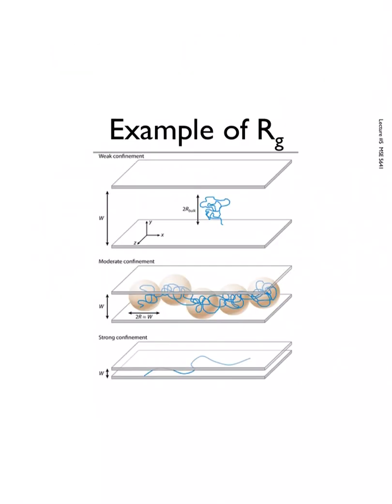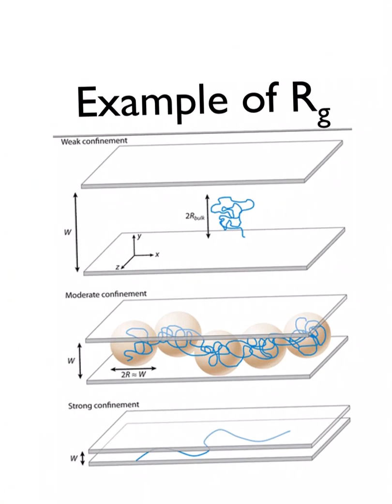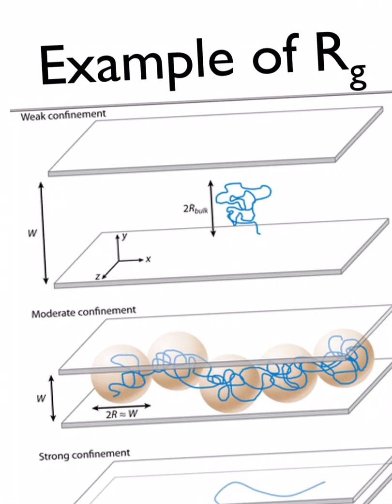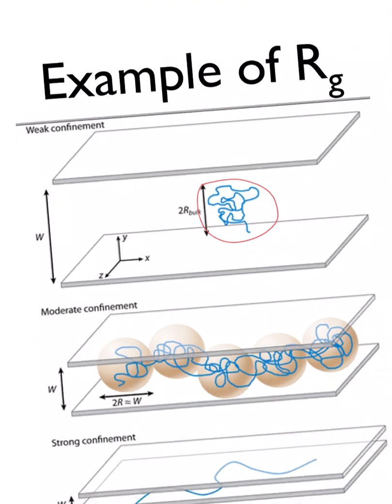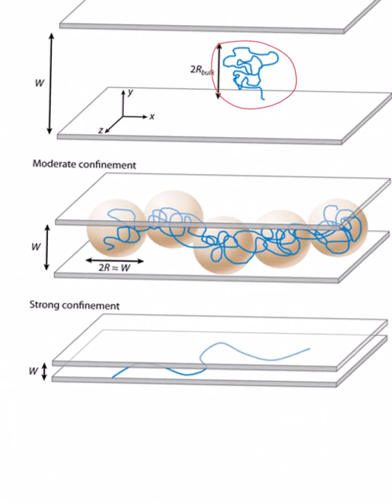And where this becomes important is, an example here is in nanocomposites. And so if we have a lonely polymer chain that is held between two plates that are very far away from it, first off, so it's very lonely, it doesn't have to worry about the plates. If we start to squeeze those plates together, then that individual polymer chain starts breaking up into individual coils. So this is the same as that initial chain, but now it's being squished by these plates that are starting to confine it. And so instead of being one blob, it kind of breaks up into many blobs instead. And then finally, if we bring things really close together, then we can actually destroy the coil structure altogether.